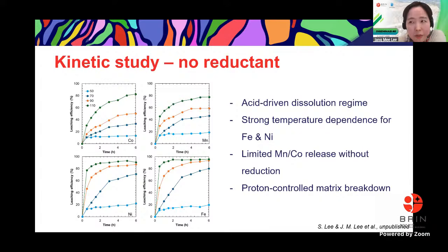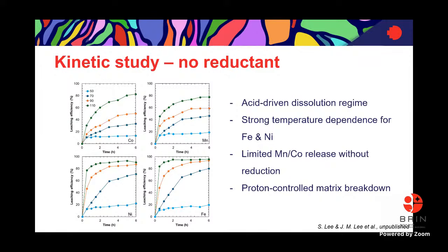How do I control the temperature? Using a temperature controller, right? What kind of thermometer do you use? Because the information on temperature is very important. In this process, you successfully found nickel recovery of about 83% at a temperature of 110 degrees Celsius, right?